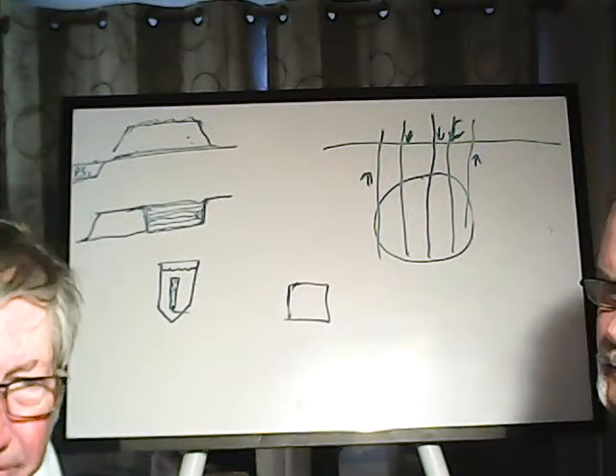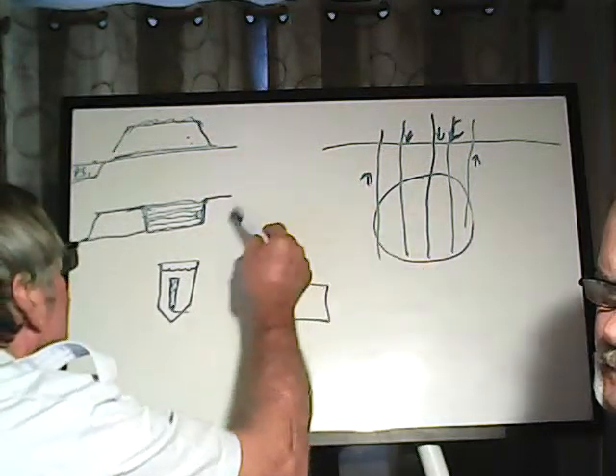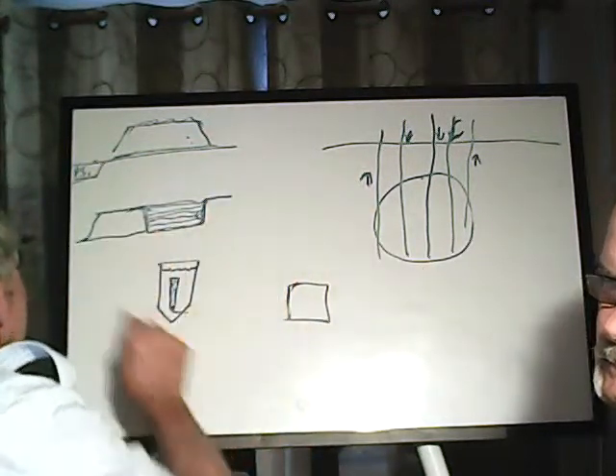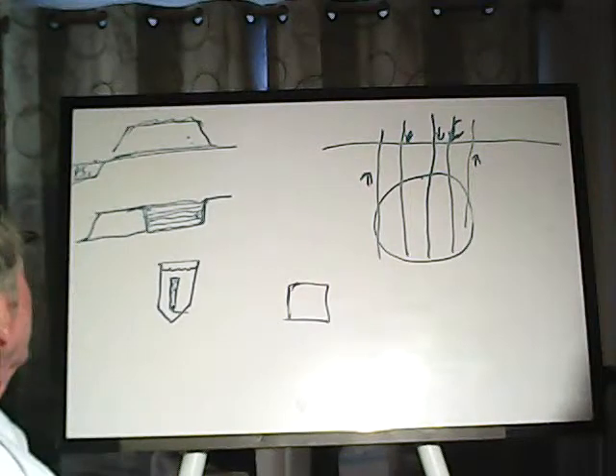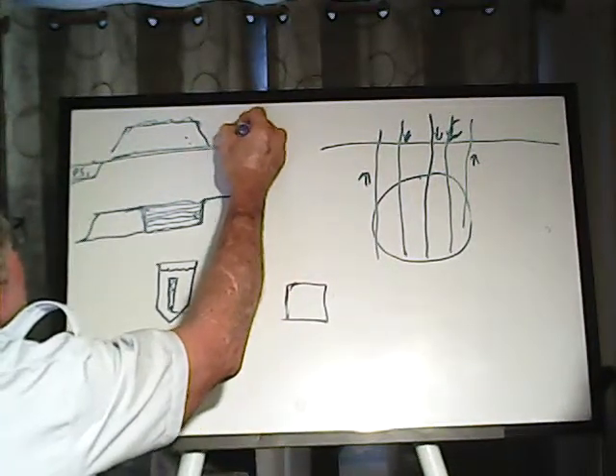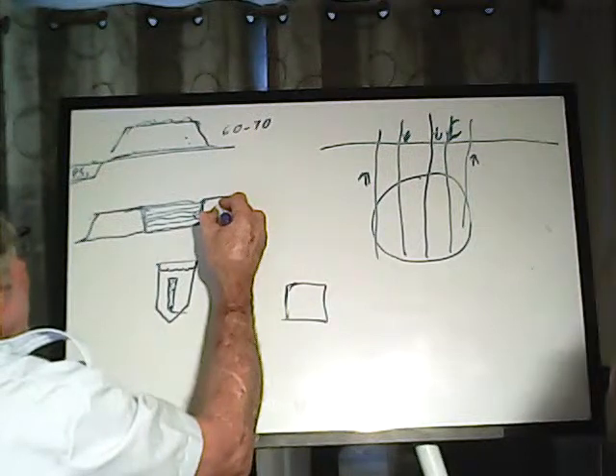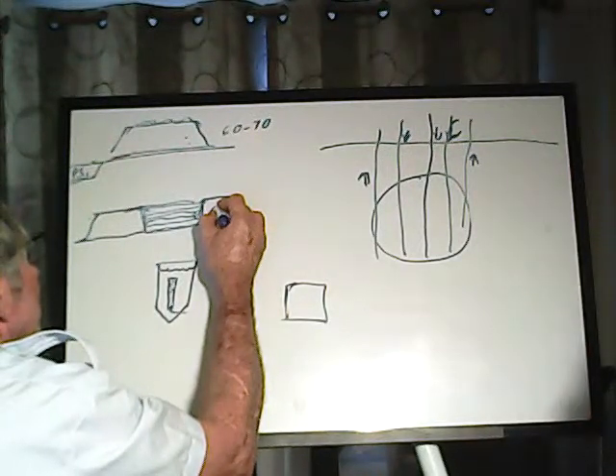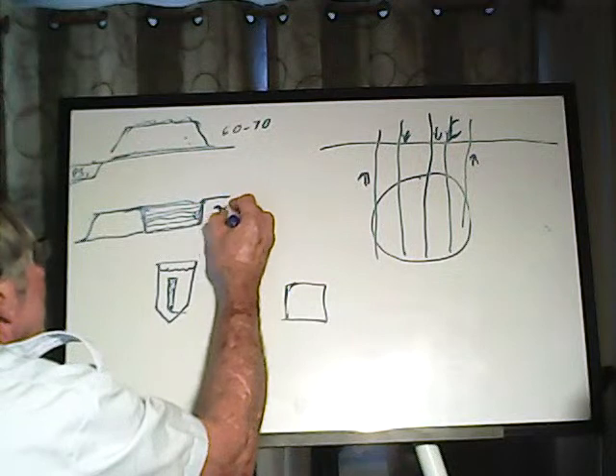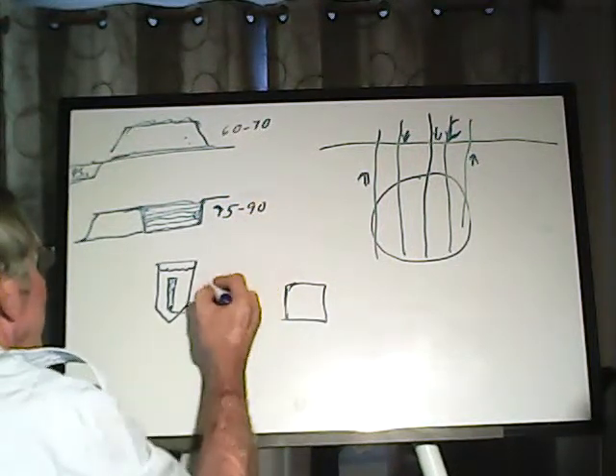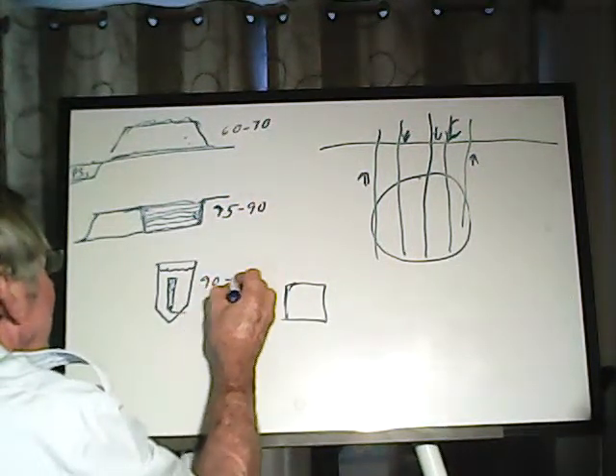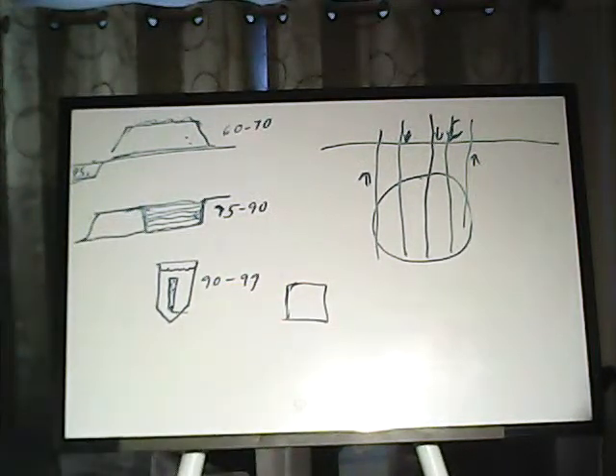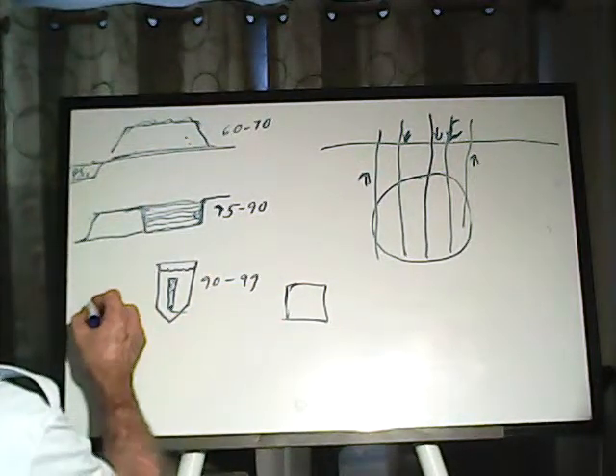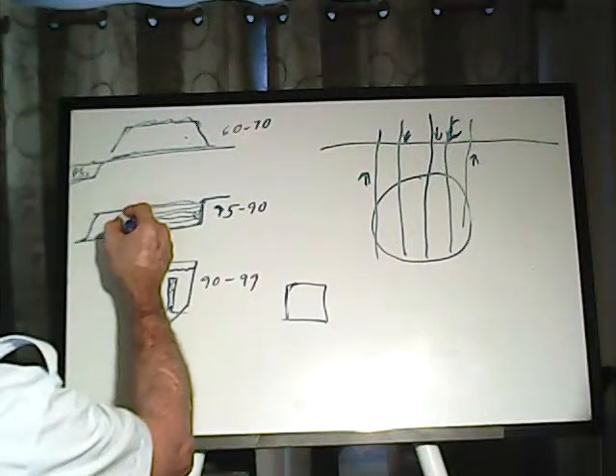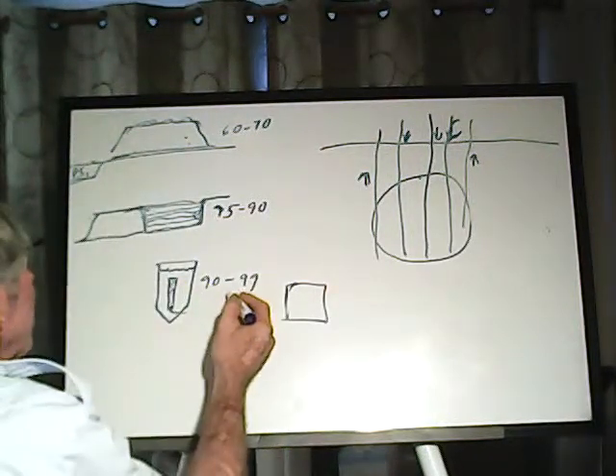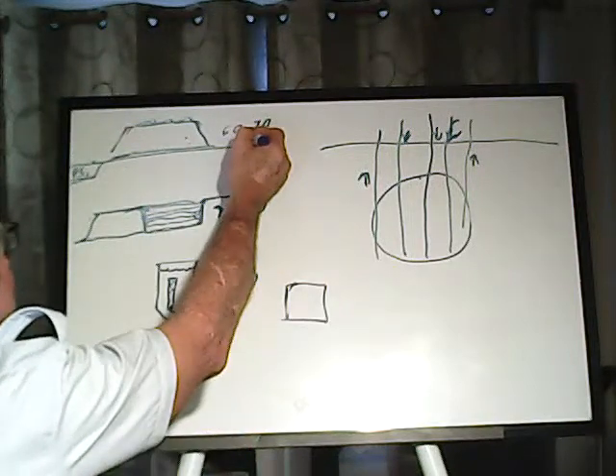And so anyhow, we're looking at possibly these two. We've got a high grade ore. This will get you like 60 to 70% recovery. This will get you maybe 75 to 90% recovery. And this will usually get you like 90 to 99% recovery. So this is more expensive, less expensive, least expensive. Best recovery, middle recovery, worst recovery.